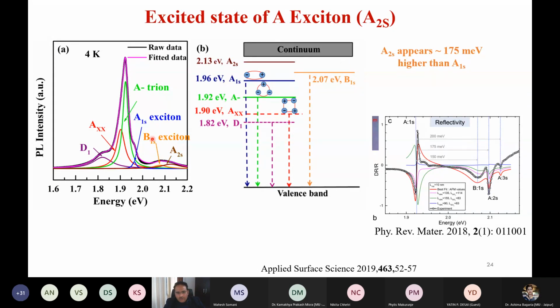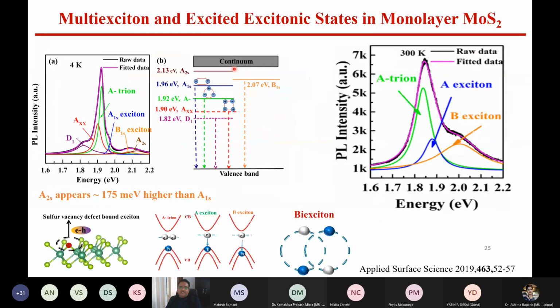While we were studying this aspect of this monolayer, research was published in this paper where they also identified that the second excited state of the A exciton will appear 175 meV above the 1s exciton. This supports our data and confirms that we are able to observe this excited state of molybdenum disulfide.